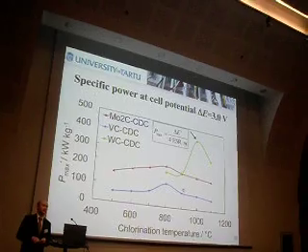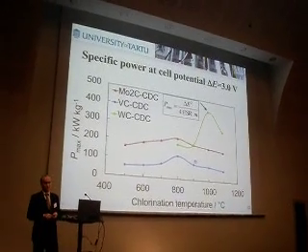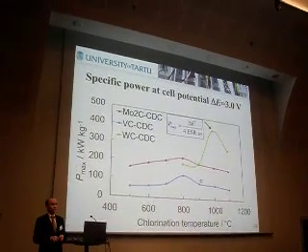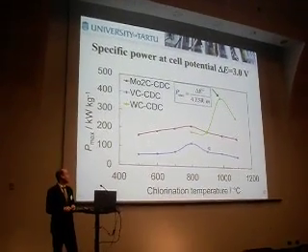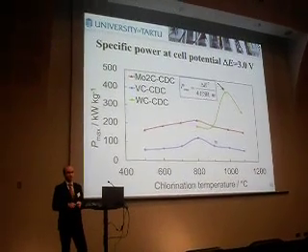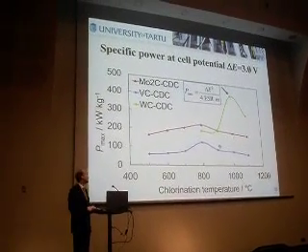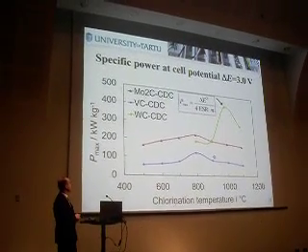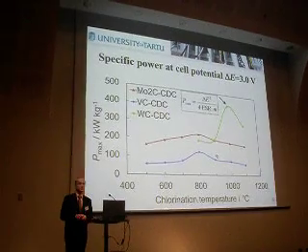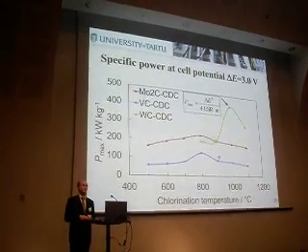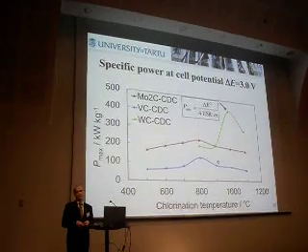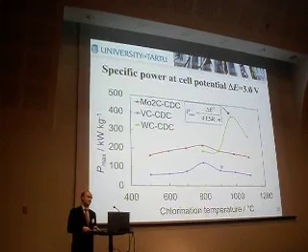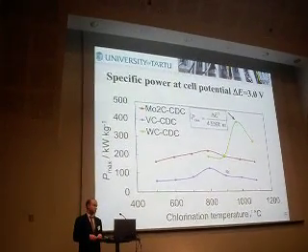But what is interesting is that when we compare the specific power, the material we synthesized at higher temperatures, especially at 1000 degrees, showed a maximum specific power about 2 times better than other carbide-derived carbons that were synthesized before by other groups.